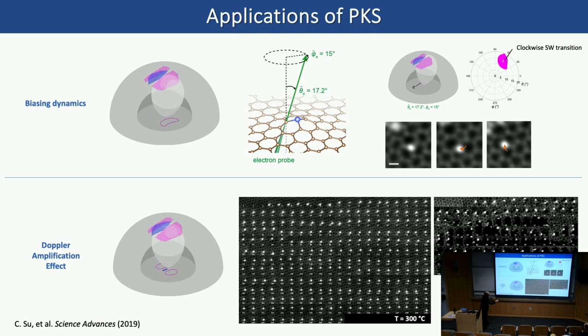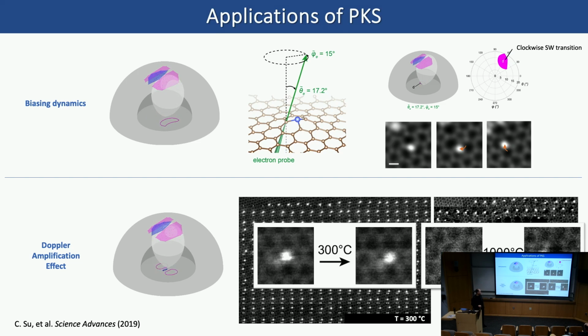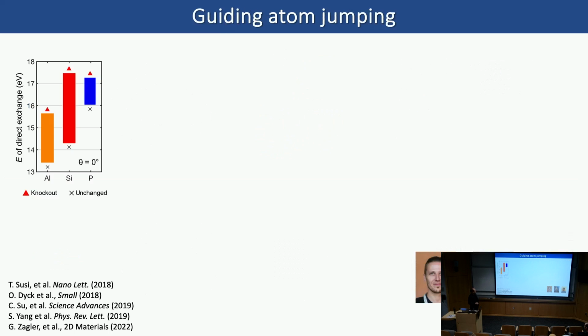At a lower temperature, these are all the frames showing one single dopant that's sustained across 251 frames. But once we change the temperature to 1,000 Celsius and we emit the same dopant, it just got knocked away almost instantaneously. So there is definitely a temperature-dependent atom displacement here. So those are some of the very intuitive ways of applying the PKS.